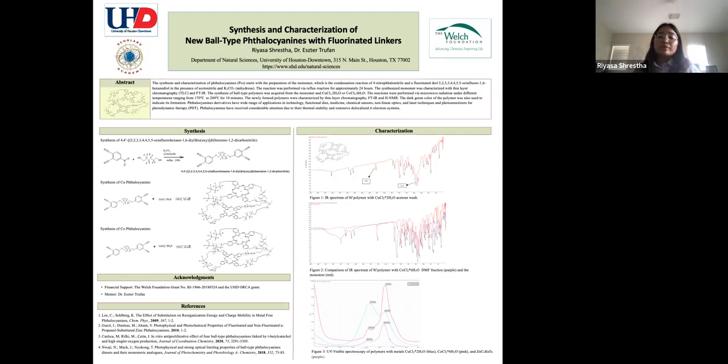In order to purify this and see no peak at all, we use TLC and separation to purify our compounds as much as possible, and used IR to characterize it again and compare it with the monomer. The third figure shows the UV-visible spectroscopy of the 3 different metals used. The zinc acetate was used by a past student.